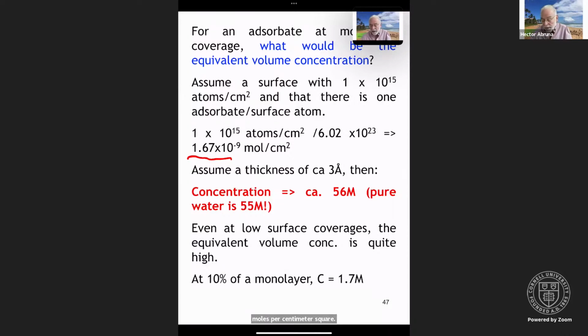If you assume a thickness of 3 angstroms, which is a typical atom size, then you will come up with a concentration that is 56 molar. Let me repeat that. One monolayer of one adsorbate, where you have 1 atom per surface atom site, has an equivalent volume concentration of 56 molar. Pure water is 55 molar. And so when you think of the consequences of having a monolayer of an adsorbate, it's enormous. It's difficult to conceive of that because we're used to thinking, well, how much could a monolayer be? After all, it's only 1 atom or molecule thick. Sure, but the volumetric equivalent is enormously large.